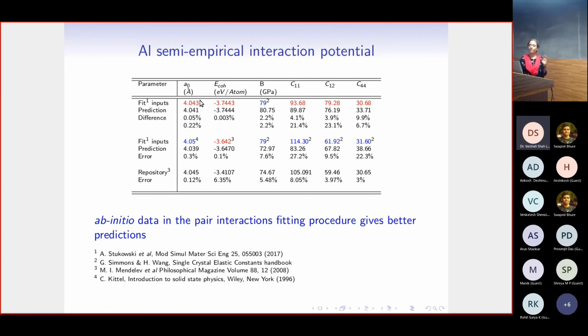So we see that it gives us a good prediction for the structural parameters. The structure it is predicting nicely: 4.043, it gives us 4.041, which is very nice. If we look at the cohesive energy, they are also agreeing very nicely. But when it comes to the elastic constant, there is a variation. This difference is with respect to these red numbers that I have shown.